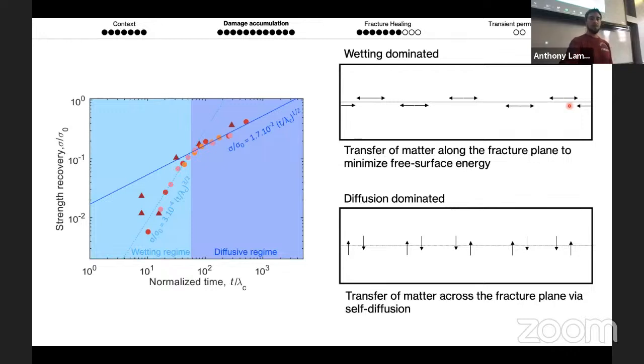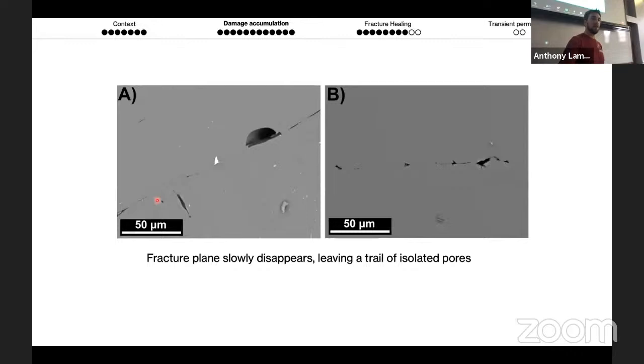So we can see that in our experimental product. So this is a natural obsidian where we see that there was a fracture, and then you can see that this fracture starts disappearing at places. And this is one of our experimental glass rods, where you see these trails of pores that are being trapped in between solid glasses. And that's the remnant of the healed fracture plane. And that leaves basically a trail of isolated pores.